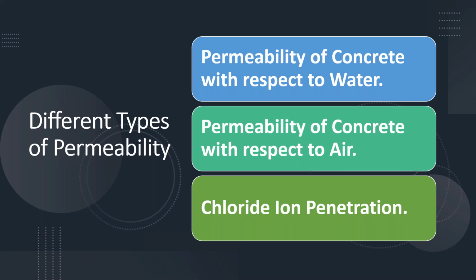Okay, when we say the permeability of the concrete, with respect to what? Permeability of concrete with respect to water, or with respect to air, or with chloride. Nowadays we are developing M80 or M100 concretes. Then measuring the permeability of the concrete with respect to water is impossible, because the relation is not clear. The easiest way is to measure the permeability of the concrete in terms of chloride penetration. That is RCPT. We did some work in this area.